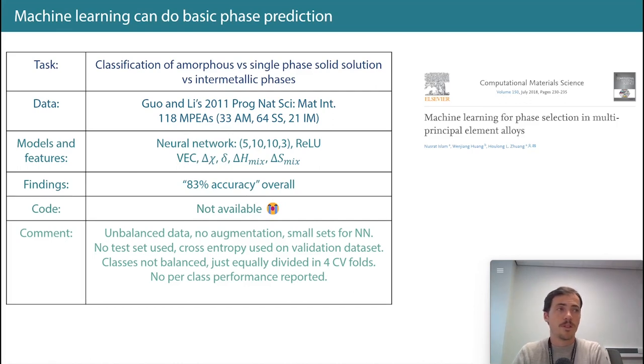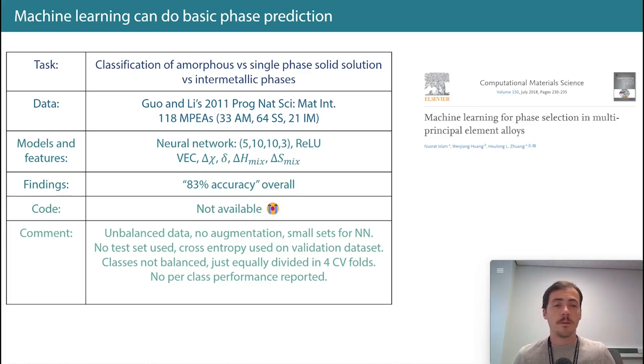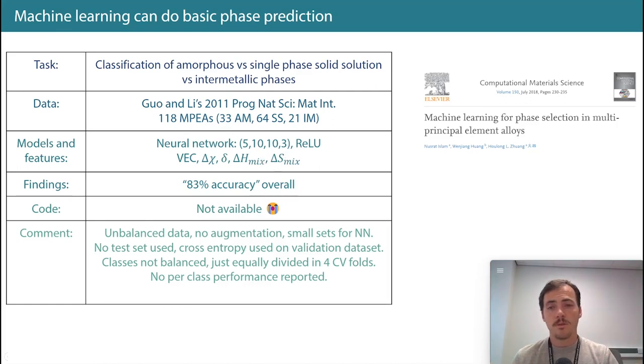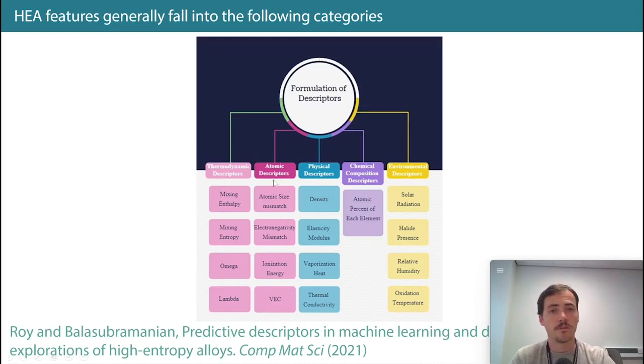Additionally, because early papers suggested that entropy — specifically the configurational entropy when forming a mixture of many components — was a stabilizing force that made solid solubility more favorable energetically than intermetallics, that's why features like ΔS_mix and ΔH_mix became popular. Those features show up over and over in the literature.